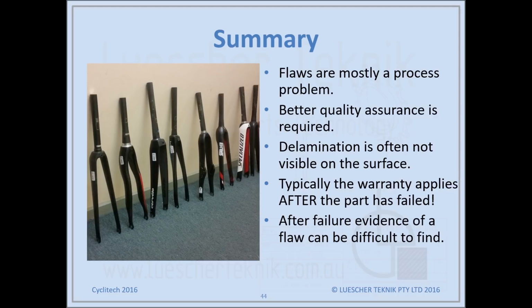So to quickly summarize a lot of this stuff, the flaws are primarily process related. So if you use the same process, you're susceptible to the same types of flaws. Better quality assurance is required to prevent some of these in-service failures. So if there are voids or porosity or wrinkles in the part, these should be identified during manufacture and not during in-service failures. Delamination is mostly not visible on the surface. Same with planar voids, these sorts of things. So they're very difficult to see from a visual inspection on the surface. You often need more information than that.